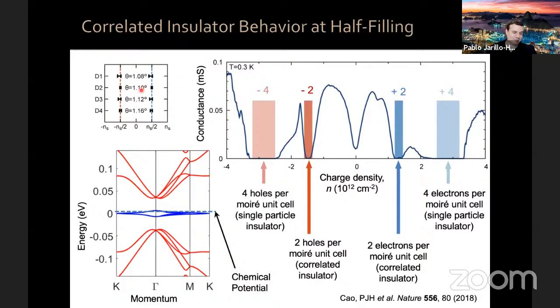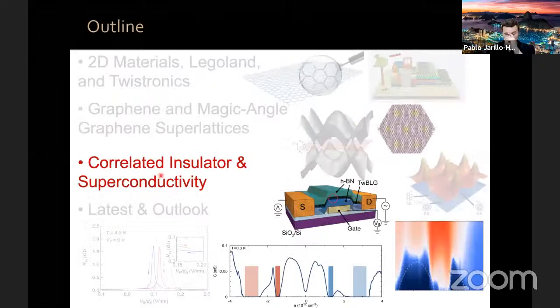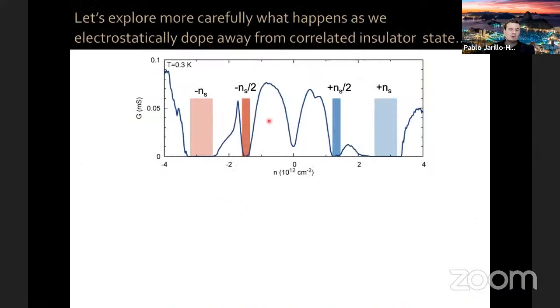So that's about the correlated insulators. Let me show you now what happens when we add carriers to these correlated insulators. I remind you this is conductance versus charge density. By the way, I didn't mention it earlier, but near charge neutrality you have this V shape because this is still sort of graphene, it keeps that graphene character at exactly charge neutrality. Now, NS is the superlattice density for electrons per Moiré unit cell. This is 4 holes per Moiré unit cell. This is 2 electrons per Moiré unit cell correlated insulator, and 2 holes per Moiré unit cell correlated insulator.